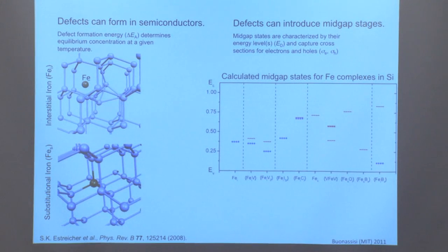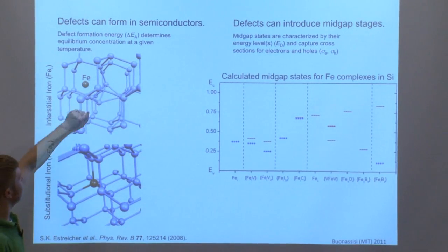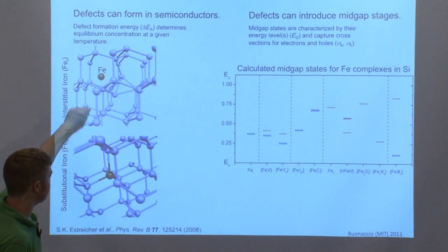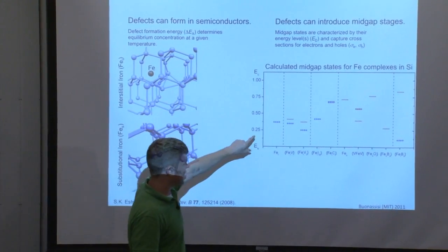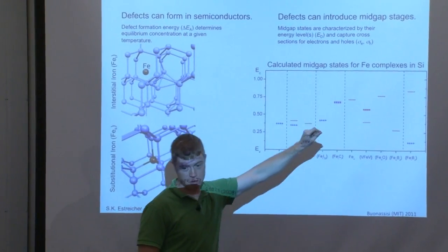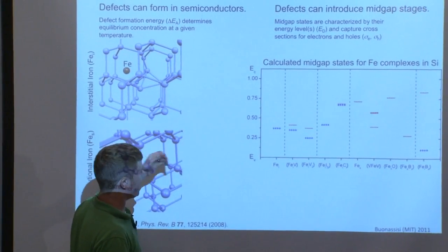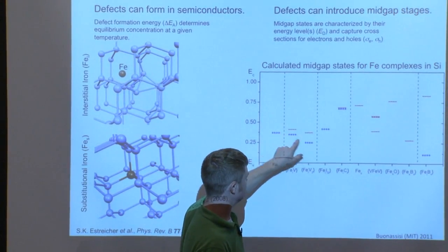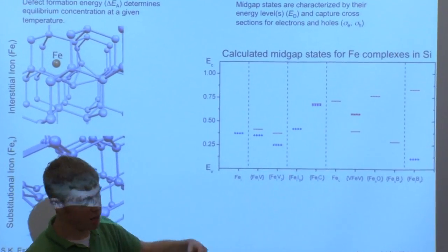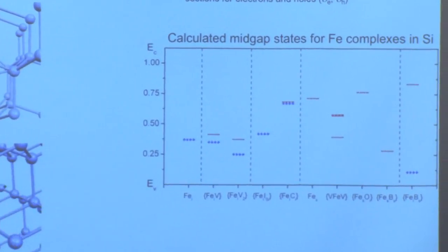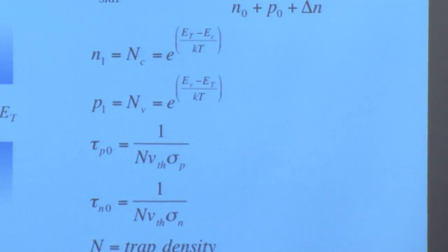And it shocked me. Anyhow, basically what we're trying to say here is that you have iron atoms, and they can sit in different areas of your lattice, but you have these defects that exist, and they introduce different energy levels within the band gap, right? So the outer electrons of iron can either sit at these sites, these blue sites, where they're donors, or they can create acceptor states, kind of like boron does, but they're much higher up into the gap. And these act as recombination centers, and we'll talk about why that is in a second.